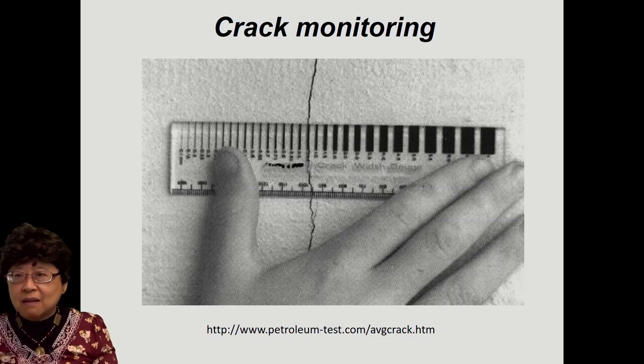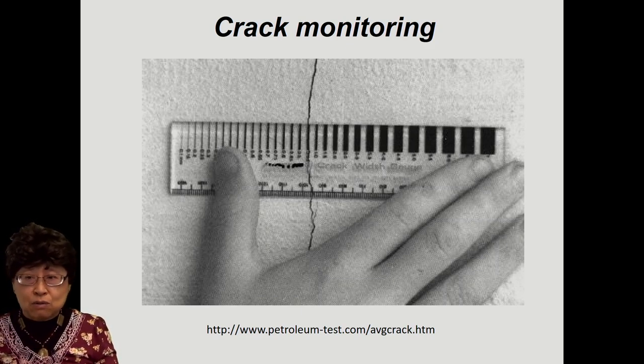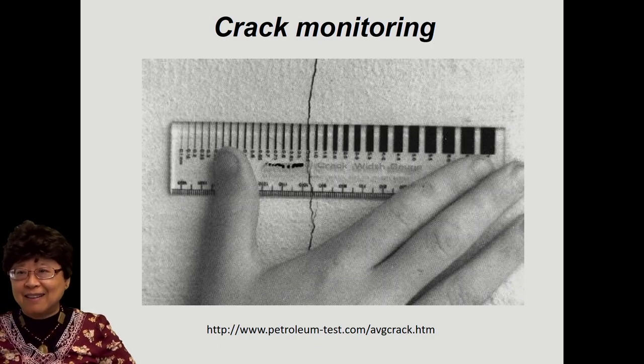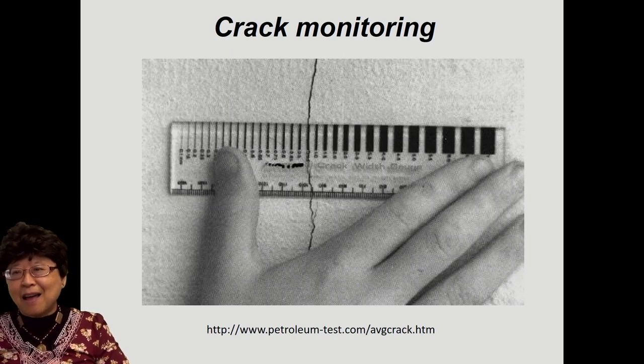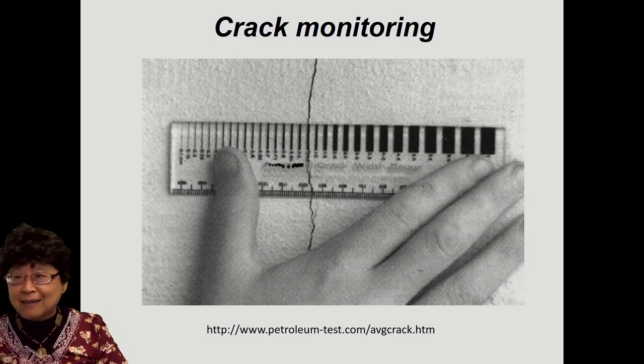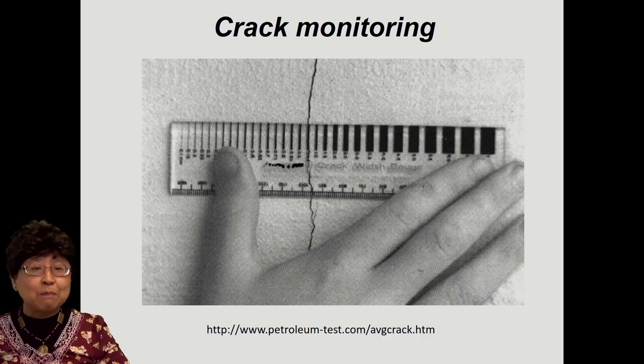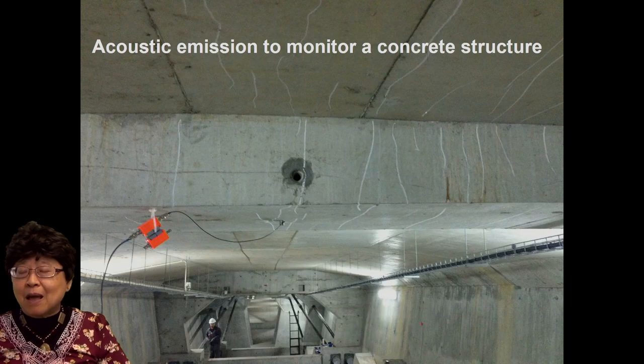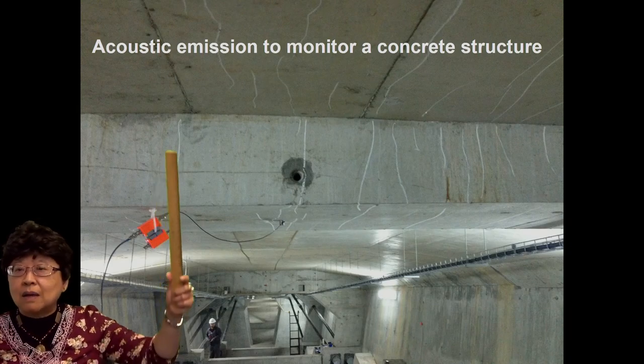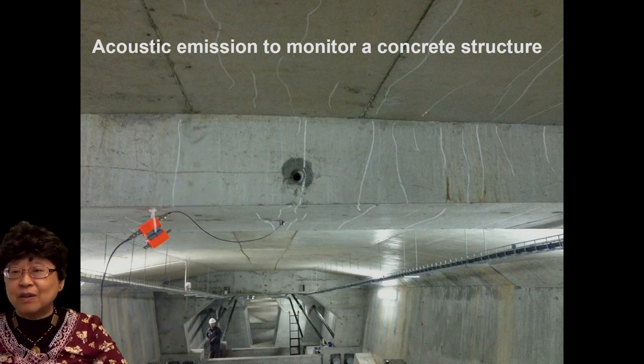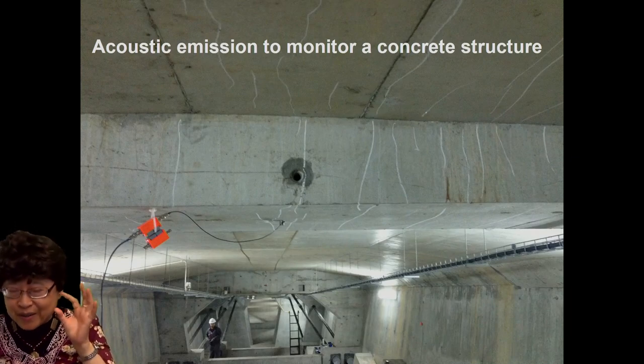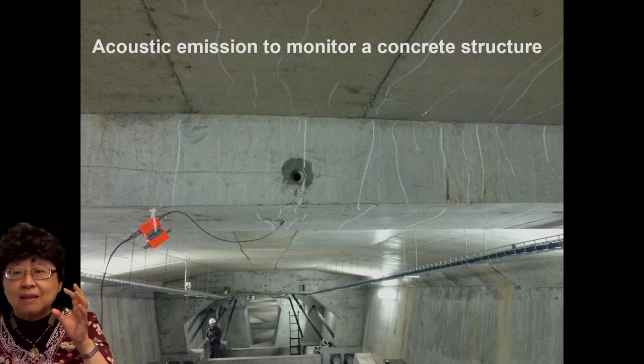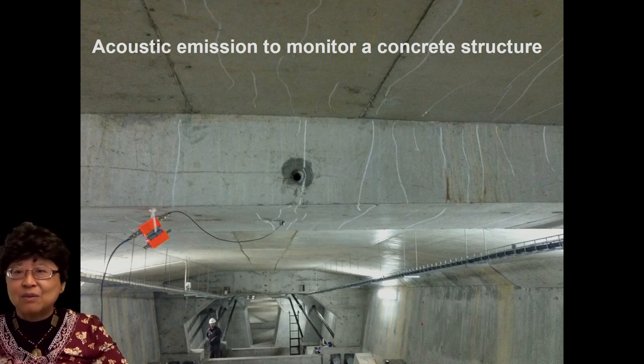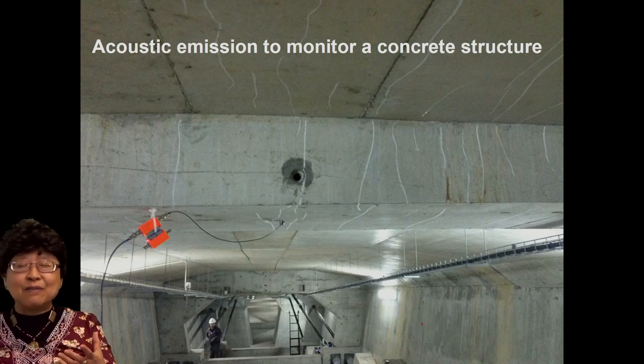And so how does one monitor the health of a structure? Well, measuring the crack width is one way, but that's not very sensitive. It'd be nice if you can detect the damage before the crack becomes visible. Okay. Another way, a better way than just measuring the crack width, is to use what's called acoustic emission, which is using a sensor, a transducer, to hear the sound that comes out during the cracking. Now this turns out to be ultrasonic sound, which makes it more sensitive than the audible sound.